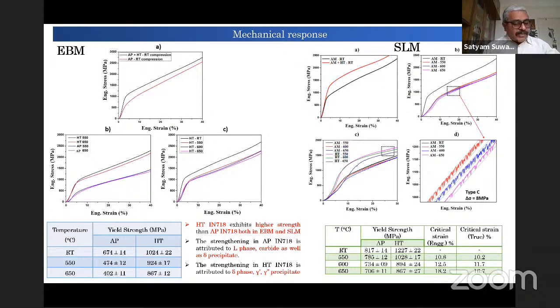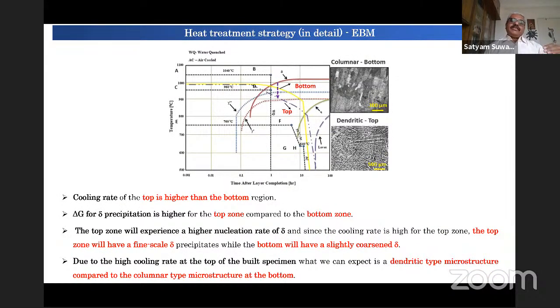Evaluating mechanical properties, we have realized that we have differences in heat treated conditions of both these materials from their as printed counterparts. So adequate heat treatment is a necessity for each of these processes separately. So no common thing can be prescribed for both. And we have seen very subtle differences in terms of heat treatment conditions also. I'm not going into detail, and these heat treatment conditions have to be optimized based on the stability of precipitates, as we have done in this case.